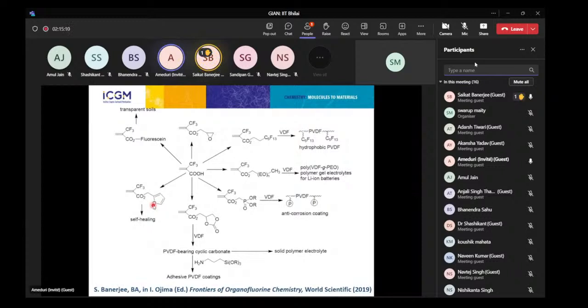Okay, but it depends what the cross-linking agent is and at which temperature it allows cross-linking. Could you give me more information on the cross-linking agent? No, actually, this is confidential. Like the normal conventional cross-linking agents already available in literature, like bisphenol A, a bisphenol derivative. So you have to work at least at 80 or 100 Celsius to favor that.